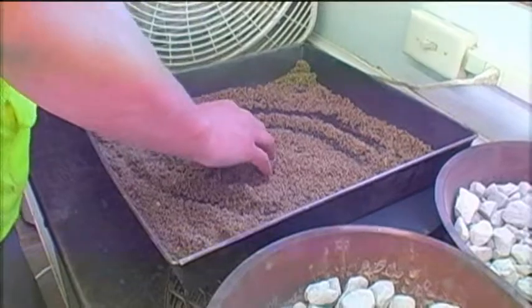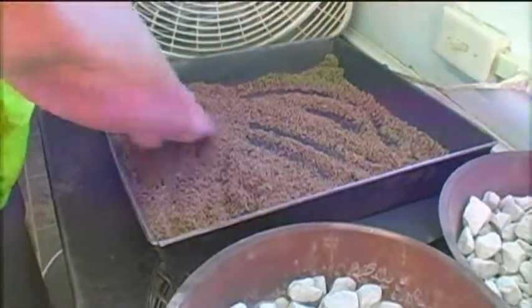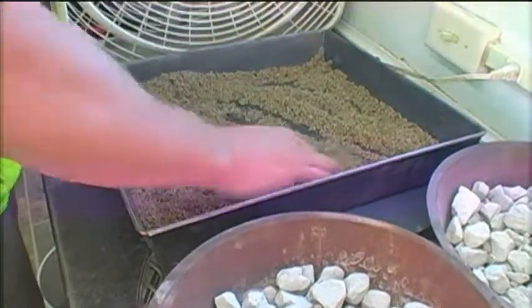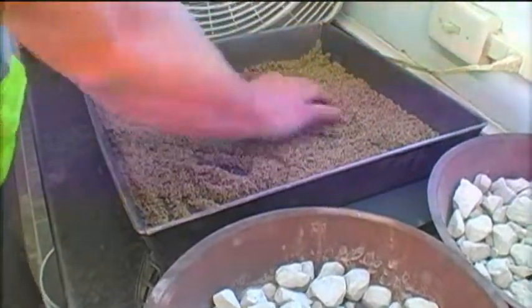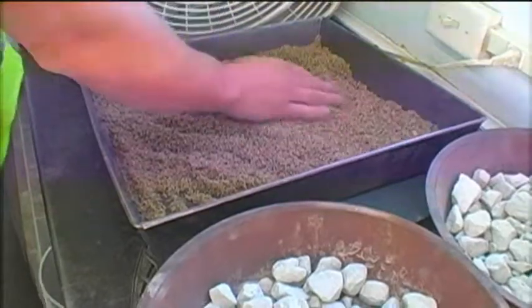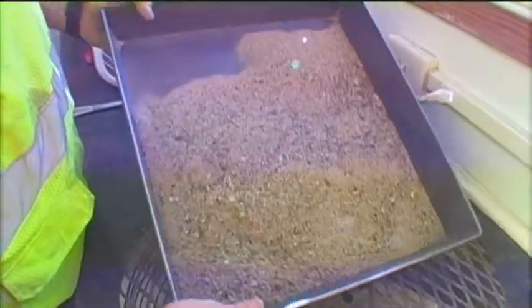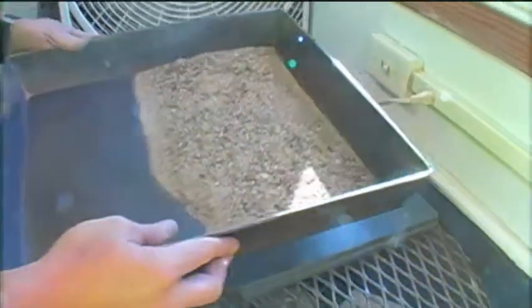As you can see, we are not quite there yet but are getting close. This will change fast, so stay with it and don't let it go into absorption. Keep stirring the material back and forth. Be careful not to have the fan on too high, as this can blow out a lot of the fines. We are just about ready. When all the particles slide easily and in your judgment it is saturated surface dry, weigh up 1,000 grams as quickly as possible.